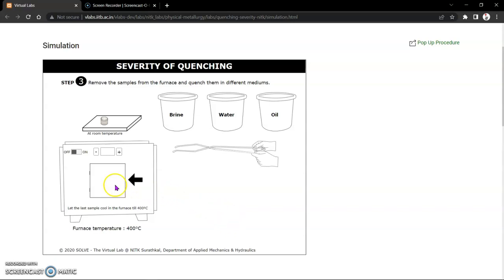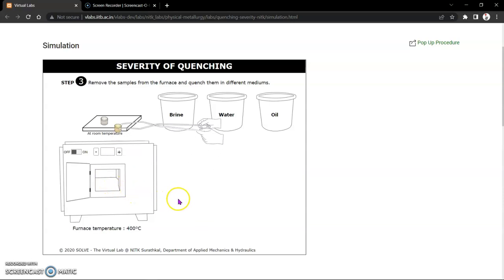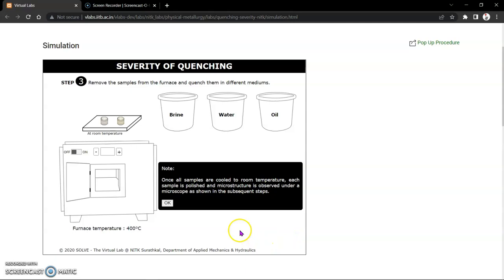After it has cooled, open the furnace and put the sample at room temperature. Note: once all samples are cooled to room temperature, each sample is polished and the microstructure is observed under a microscope, as shown in the subsequent steps.